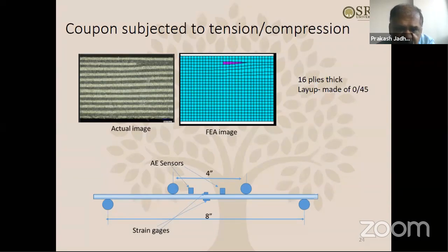You can see when the sound events actually start, and as the crack propagates, more and more sound events come. At a certain stage, the sound events suddenly start appearing, and then as the crack propagates, they increase exponentially. So you can plot acoustic emission events over time and find when the crack initiation happened. That load level, when the crack initiation happens, is very important, so we tried to find it using this.